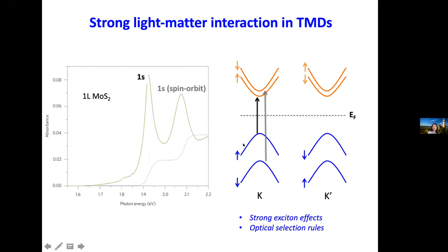Monolayer TMDs interact very strongly with light, and the optical response is dominated by the strong exciton peaks. You will see a little bit later, so this gives optics as a very sensitive probe of the system. There are also very interesting optical selection rules that couple circularly polarized light of opposite handedness exclusively to the spin valley degree of freedom. And if you look at the difference between left and right circular polarized light absorption, you get a probe of the net magnetization in the system. And this you're also going to see a little bit later can be used to probe the magnetic properties of the system.